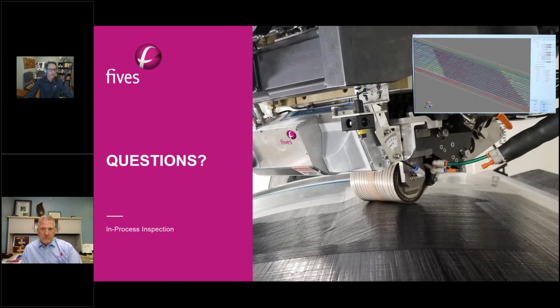We have to look at it at all the different angles, so you have to really look at the worst case presentation to the sensor. You can't just use the best case presentation. And then the defects from a topical standpoint, it's really the height, which is about 1 tow dimension, which is 5/1000ths. Thickness dimension.